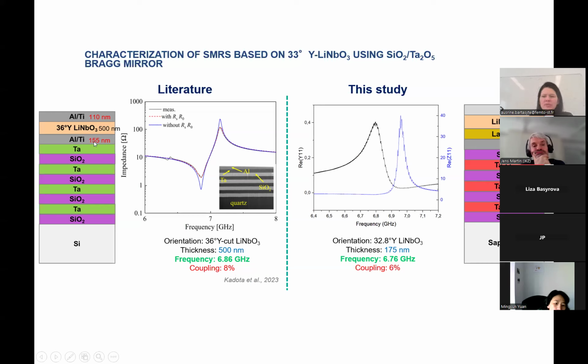We also had some problems with the fabrication, if I remember well, on the mirror or something like this. We had a problem with fabrication on this device too. And you see my film is much thinner, so I would already expect much lower coupling, and my electrode is very heavy platinum, so the coupling is killed as well. So the coupling of the film is not that bad if we compare it. It's relatively comparable. But we need to redo everything more properly to show the real performance of these films.